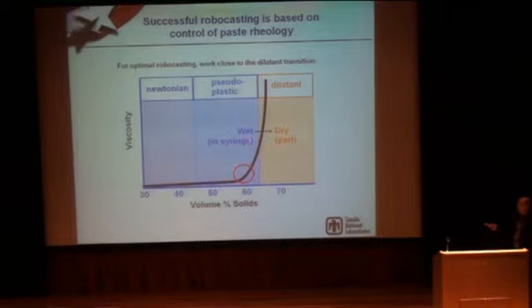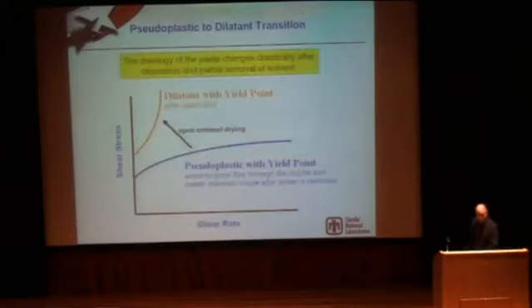In this state, it's dilating, and dilating is a situation like wet sand on a beach, where everything's wet and saturated, but if you were to smack it, it feels like cement. It makes it more like a solid. And that's what we're doing. So after it comes out, there's a little bit of evaporation, and living in Mexico with a humidity of about 10%, you can get this transition to occur very, very quickly.